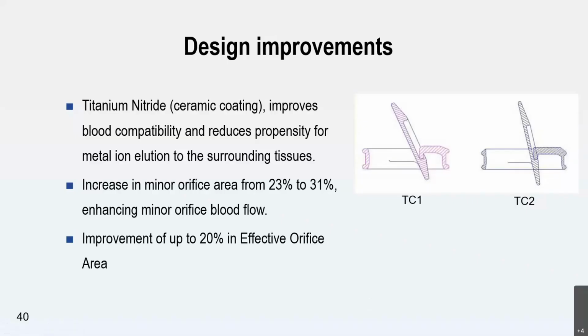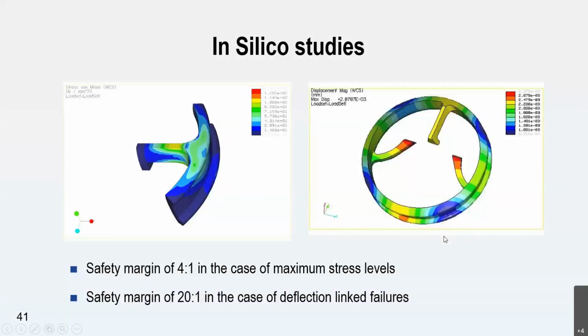So the primary design improvements included a titanium nitride coating, which improves the blood compatibility, then increasing the minor orifice area from 23% to 31%, and an improvement of 20% in effective orifice area. Effective orifice area is a measure of the pressure drop across the valve. So we went through extensive studies. Actually, the in silico studies are normally carried out to make sure that the structures work properly, and we established that there is a 4:1 safety margin with respect to the stress levels and a 20:1 safety margin with respect to the deflection linked failures.